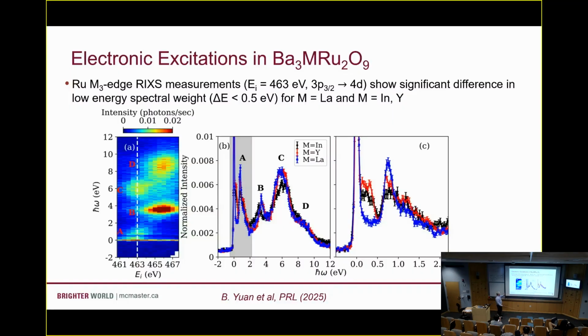The ruthenium M-edge, we're probing the valence levels, and again, if you look at a map here showing the resonance behavior, this is for the yttrium compound here. Here we've got a slightly larger energy range that we've measured. Again, though, you can see features that resonate at around 463 here and here, and features that resonate around 466 here and here. Okay, so these are the features that we're associating with excitations into the T2G levels, these excitations into the EG levels. Okay, so down here, this is intra-T2G excitations, this is T2G to EG, and these are charge transfer excitations. So this is taking charge from the oxygen P levels and either going to T2G or EG levels.